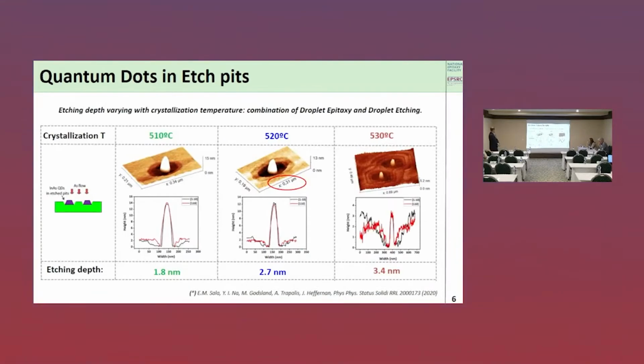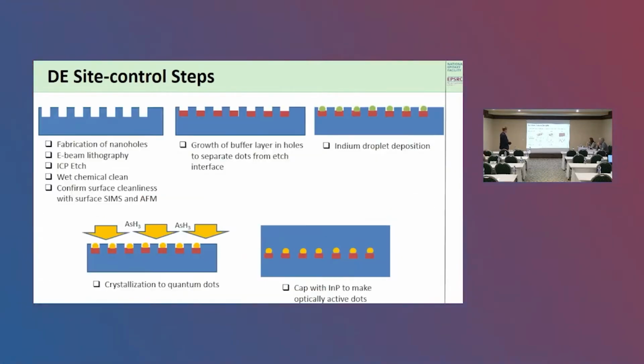Just to indicate that we've got some control over this, you can see that at different growth temperatures the dot again appears inside a nanohole, usually a few nanometers deep, but note the scale here. These pits are of the order of about 300 nanometers, so the pit is about the same scale as that used for the seeding of the quantum dots in nanoholes. So the interaction of this natural etching process with our fabricated nanoholes is of interest, and could allow us to control the shape of the quantum dots.